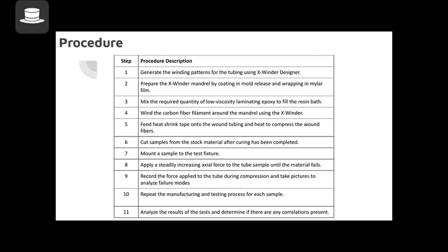We would then cut samples from the stock material after it had been cured for approximately 12 to 24 hours, mount the sample in the test fixture after it was cut, and then apply steadily increasing force until the sample would fail. We would record the values of compression as well as take pictures to analyze the failure modes. We would repeat the manufacturing process for each sample and then analyze the results to determine our correlations.